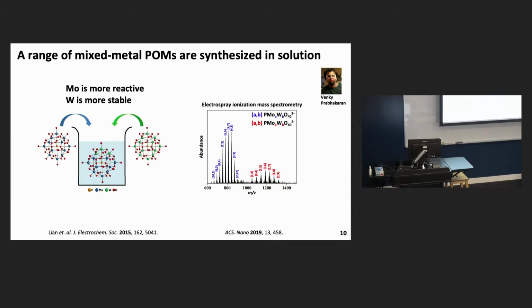So you can combine these two species in solution, and when you do, you get a distribution of mixed clusters containing both molybdenum and tungsten atoms. And that's what's shown on the right-hand side here. And now with soft landing, we can go through and we can pick out each one of those species, isolate it from everything else, and deposit it and build a supercapacitor device just out of that. And this basically allows us to look with atom-by-atom precision how metal doping affects the performance of a supercapacitor.